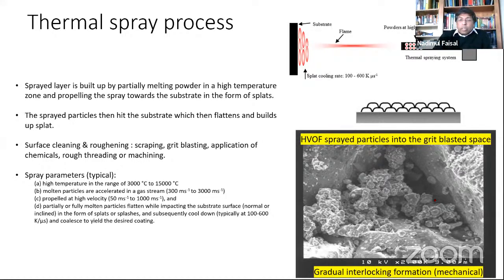Now, as you manufacture the substrate, it will have an impact on the surface you produce. So grit blasting will change the surface properties. Some of the strain will change on a very small scale, but it does have an impact. But these are necessary. If you don't do grit blasting or roughening of the surface, then the coating will not adhere. So this is the natural process we have to follow. For the different types of thermal spray techniques, we are not going into detail, but these are typical spray parameters which can be applied. One important thing to think about here is the cooling down, the quenching or splat forming process. It happens in a few milliseconds or microseconds.